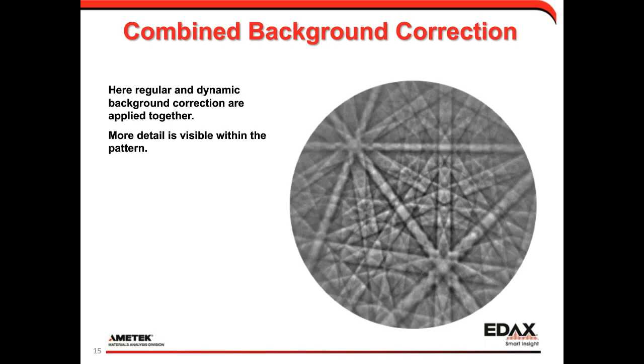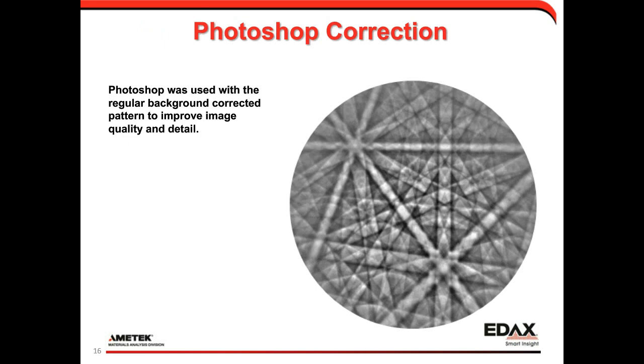And then finally, if you really want a nice-looking pattern, you can do some different image processing routines. This is an example of combining both the regular and the dynamic background correction together. You can see a little bit more detail in the pattern, a little bit more contrast. We can take that same pattern now into something like Photoshop or ImageJ, where we can adjust the contrast, adjust the brightness, and really optimize the pattern for visual appeal. But again, it's important to note that this isn't really necessary for the band detection and indexing part of the analysis.